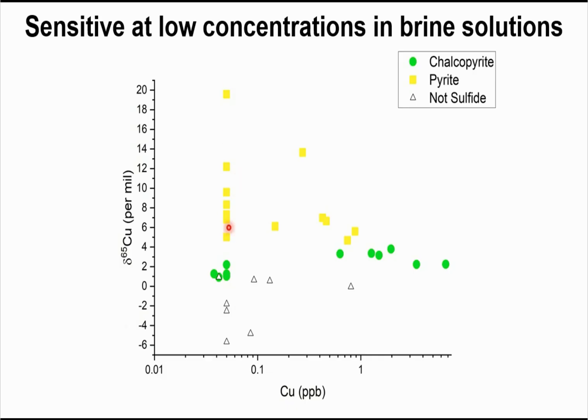In yellow is pyrite, in green is chalcopyrite, and the open triangles are not sulfide. These are copper isotope and copper compositions of water reacted with each of these three minerals. And so even at concentrations as low as tens of parts per trillion, we can detect the presence of iron sulfides and copper iron sulfides.